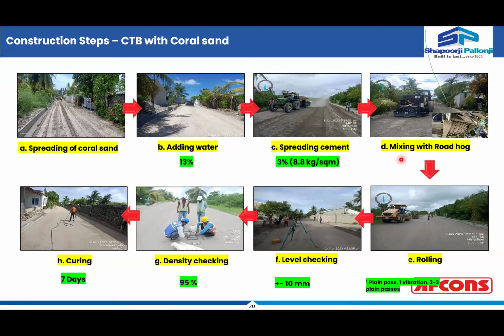Then mixing of the material on the road with rotavators will add pulverization. The better the pulverization is, the better the mix is, and the better the uniformity of the test results achieved during the lab conditions. Because the basic difference between the lab trials and the field trials lies in the pulverization area, because other things remain the same. You can control the quantities by measuring them mechanically, but when the spreading and the mixing are being done in lab conditions, you have better control. In the field, you may or may not have the better control.